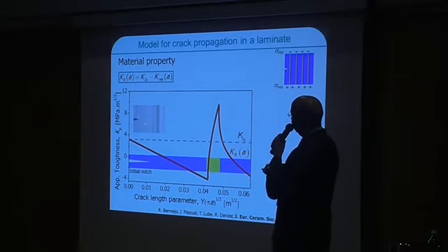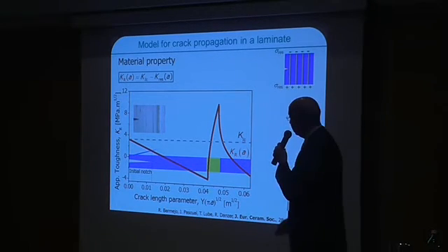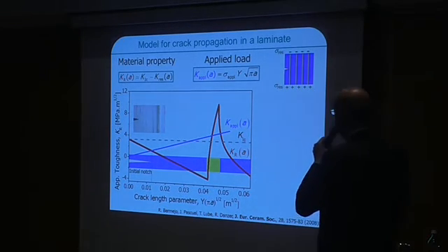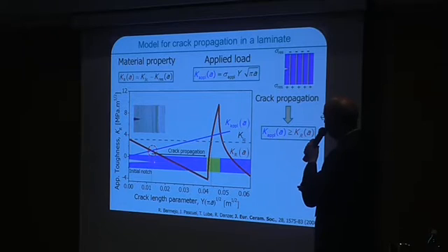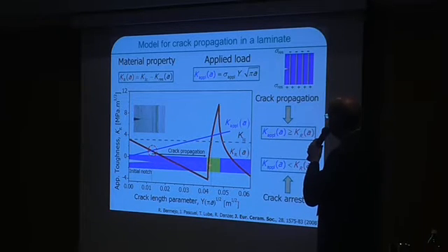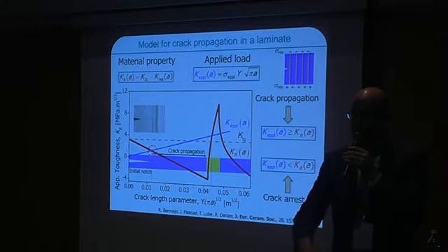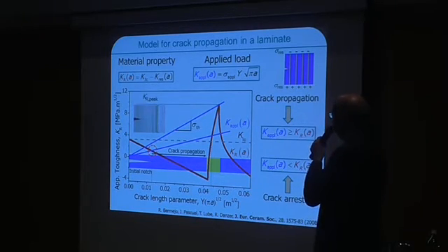So if you think about trying to explain this, here you have a notch, then you apply a certain stress, which we describe with the stress intensity factor that we apply, and a very simple criterion from Griffith: when this is overcome, then you get spontaneous crack propagation here. It will not propagate straight through, because at a certain location, this condition is no longer fulfilled. So the crack must stop there. With this very simple model, we can understand under which conditions the crack arrests.